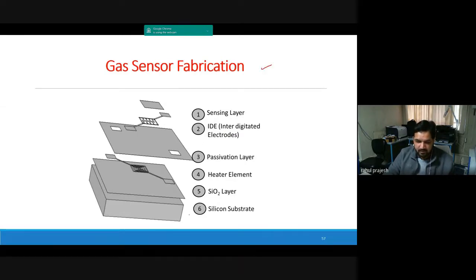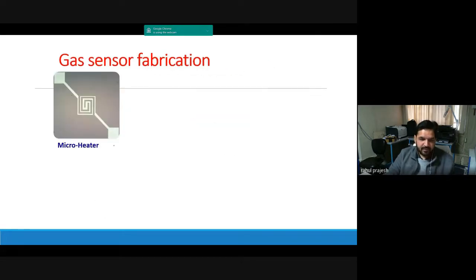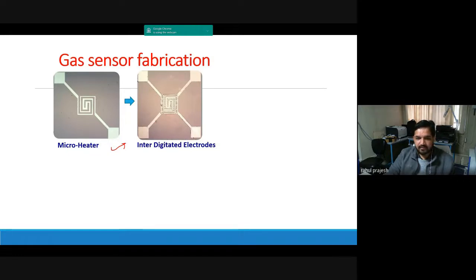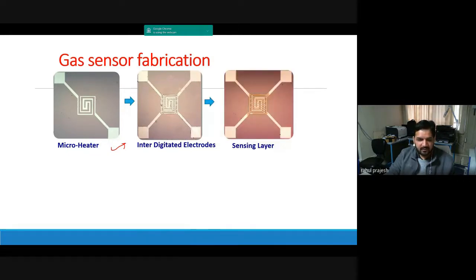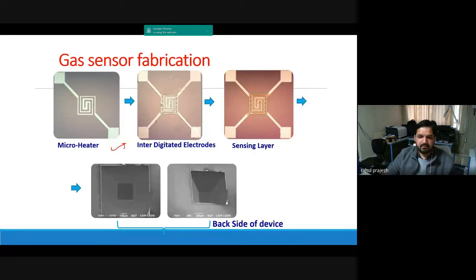And this is the sensor fabrication steps. Here you see this is the model. You have a substrate, silicon substrate. You have an isolating layer, electrical isolation layer. Then you have micro heater. These two, this is a conducting layer, and silicon is also semi-conducting. So between these two, you need to have an electrical isolation layer. Then you have interdigital electrodes, and this is also again metallic. So electrical isolation layer is required. Then you have sensing film. So this is the traditional gas sensor device made of silicon. So you make the micro heater, you pattern on that, you will make the electrodes, and you put sensing layer on the top of that, and you do backside cavity to reduce the thermal mass. So these are the different steps of gas sensor fabrication and different stages you see over here.